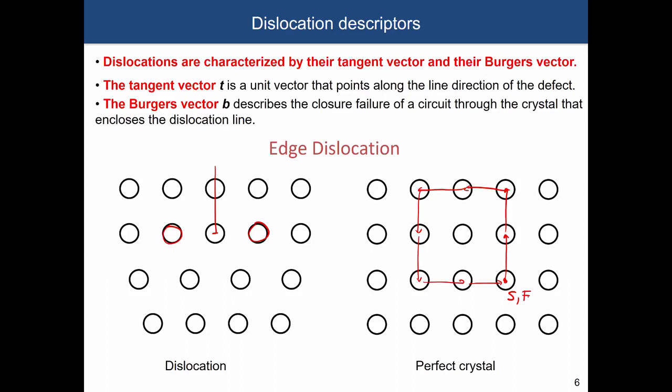You take a circle making two steps in each direction. The choice of steps is made because we have to make a circle that will surround the part of the crystal containing the dislocation — we have to make the full circle around the dislocation. The number of steps in each direction is irrelevant; the result will be the same. You first count the steps in the perfect crystal, then do the same in the non-perfect crystal that contains the dislocation, making the full circle surrounding the dislocation.